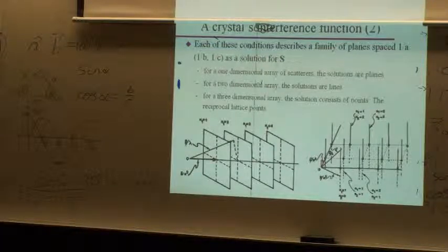In a powder pattern, all you would get would be tails to your one-dimensional data, okay? But these things can actually show up in real life. If you have nice crystals, chances are they won't. But if you have a crystal that is very limited in 1 dimension, then they might.